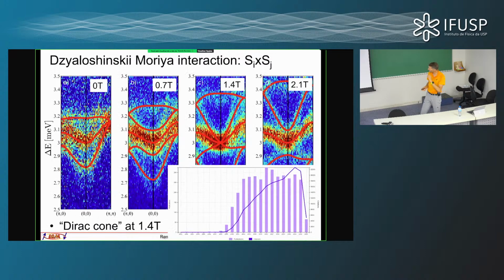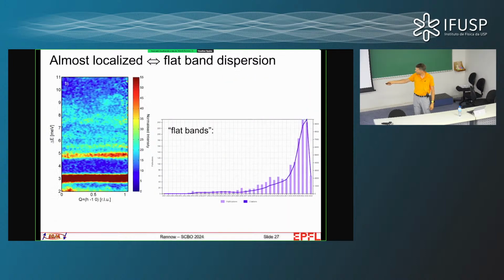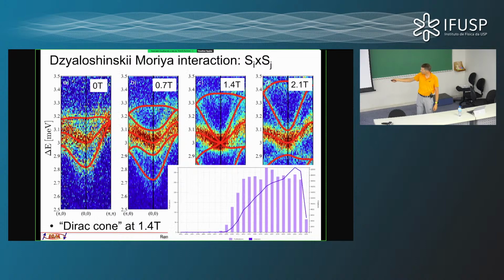Now, there's a detail that in addition to the main interaction in the system, there's also a so-called Dzyaloshinskii-Moriya interaction that couples not only the dot product between two spin operators, but also has a contribution from a term that couples the cross product between two spin operators. And what that does is that what appeared to be a flat band, when we zoom in with very high resolution, actually has a bit of dispersion, okay?